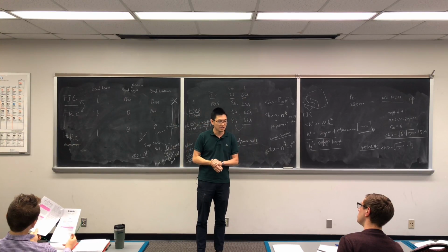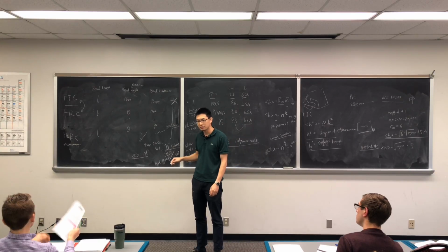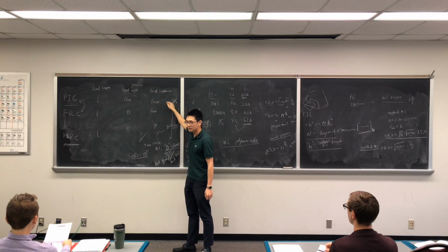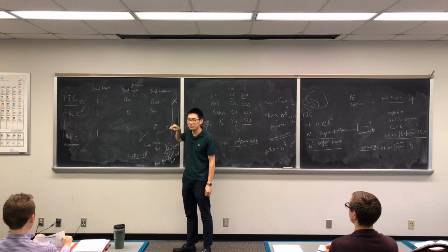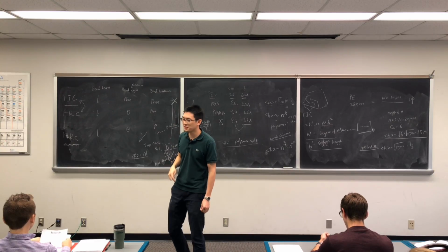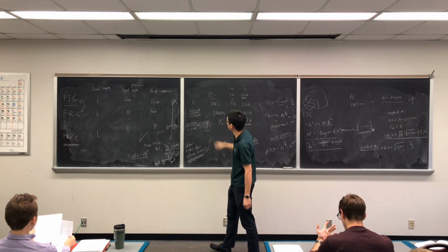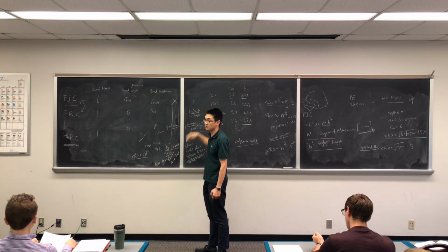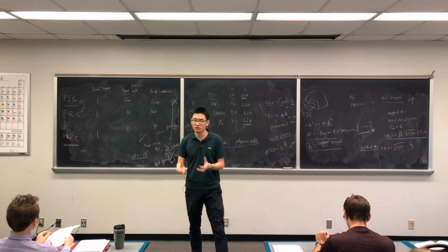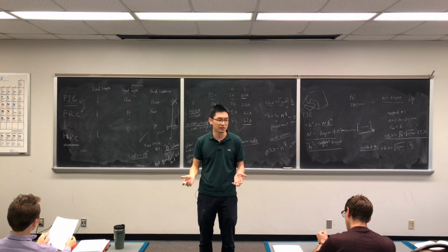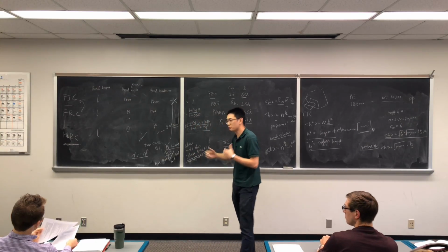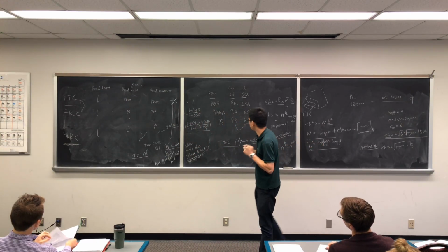For this particular lecture, we discussed in more depth these three different chain models, and we defined a few new terms. One is called the characteristic ratio, which I just erased here, which we can use to think about how rigid your chain is, because that's basically the physical meaning. The higher the characteristic ratio, the more rigid your chain will be, and the more it will extend the end-to-end distance.